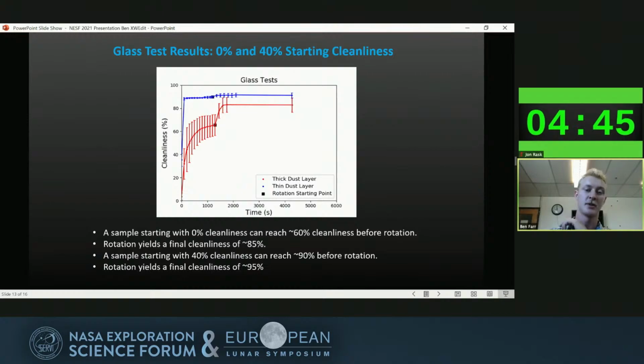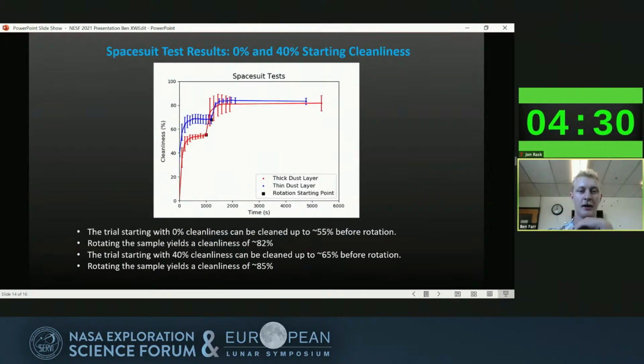So for glass with a thick layer, we found that we got an increase of about 20% with the rotation. So we jumped from 60 to about 80. And then for a thin layer, there wasn't really too much increase with the rotation, and we think that's just because it was already so clean in the first place. Pat ourselves on the back.